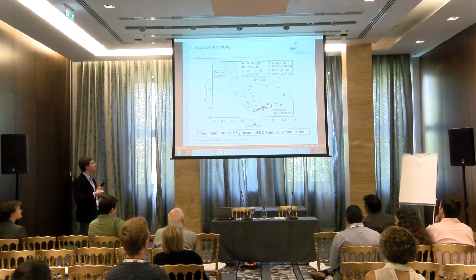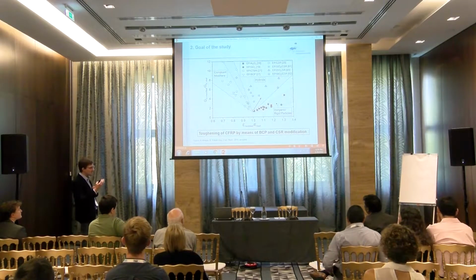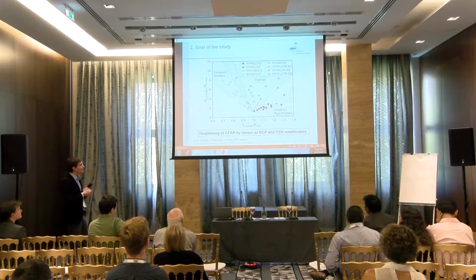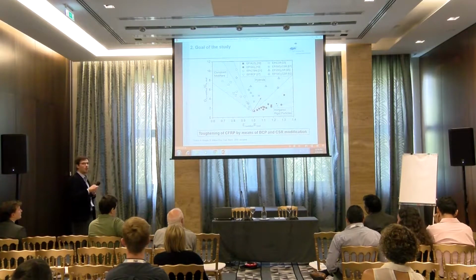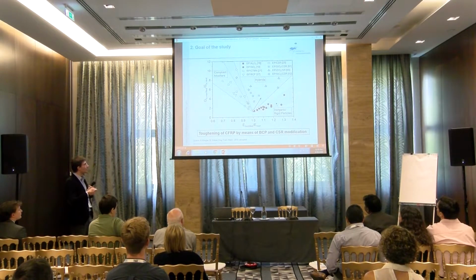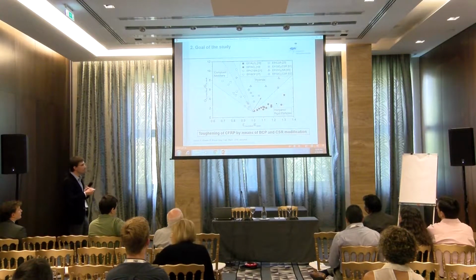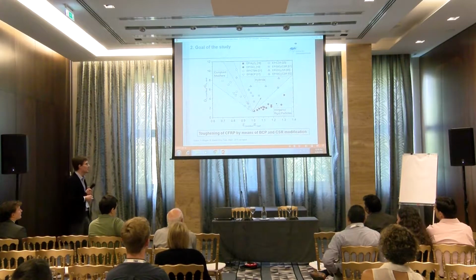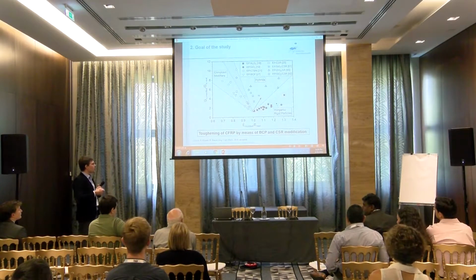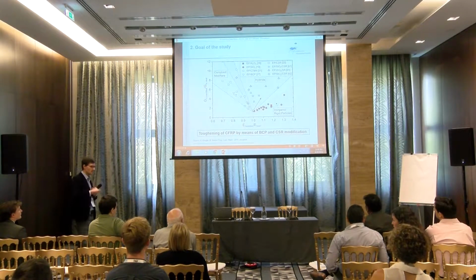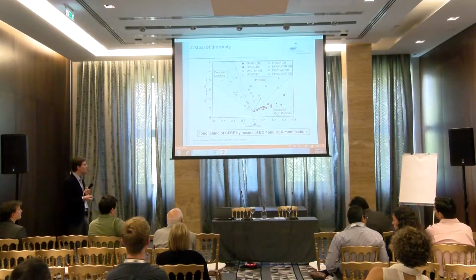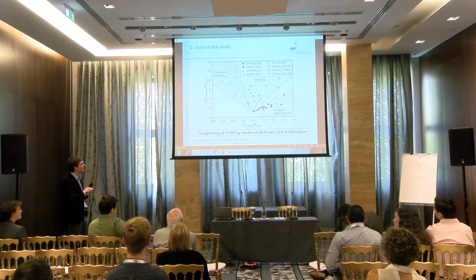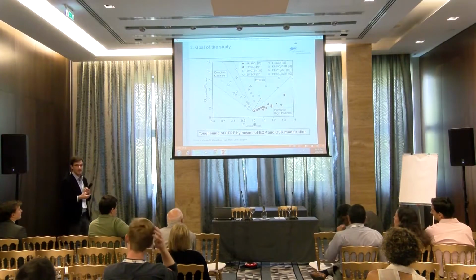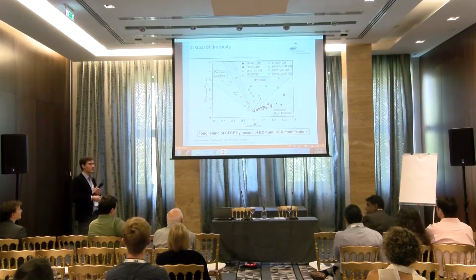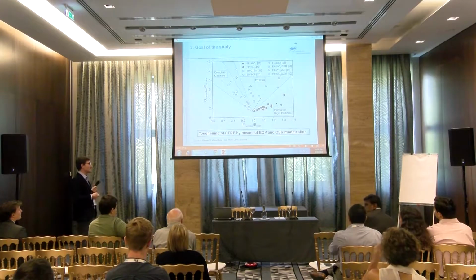Nowadays, there's a new approach using hybrids, and that was why the study was more or less inspired by hybrids to use inorganic and compliant modifiers to balance the loss in stiffness, but to get still a quite proper increase in fracture toughness, energy release rate. Toughening by block copolymers and coarser rubber particles has different other advantages, which I will show you in the next slide. However, we will expect to be somewhere here in that area, because both modifiers are rubbery modifiers, so there won't be any effect on the stiffness in that sense.